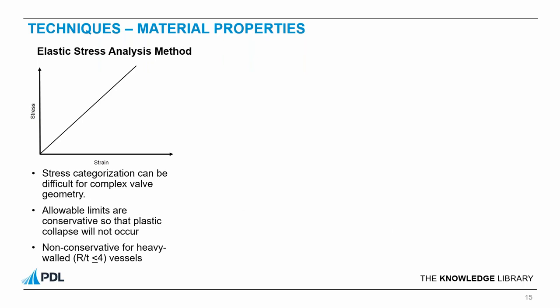So starting with the elastic stress analysis method, you post-process the results by way of categorizing the stress. This can be a little bit difficult when looking at a valve geometry, especially around the seat pocket. Allowable limits are conservative, so the plastic collapse will not occur. Just note that this is non-conservative for heavy-walled vessels, which are typically used in high-pressure applications, and therefore it is not recommended.